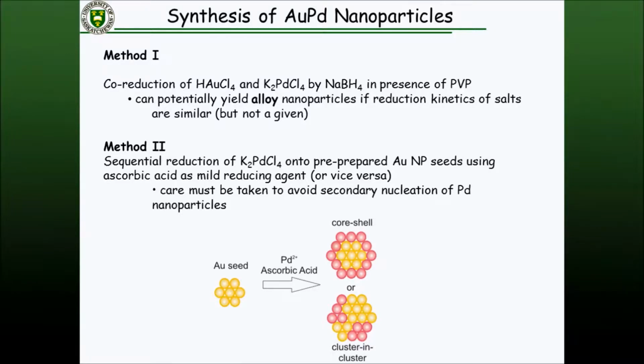Both gold chloride and palladium chloride salts reduce almost instantaneously in water with sodium borohydride. Because both have very fast reduction kinetics, this is potentially a way of making alloy particles. I say potentially because we've done a lot of characterization, and the particles you do get are actually very close to being alloys. I'll talk about how we do that.